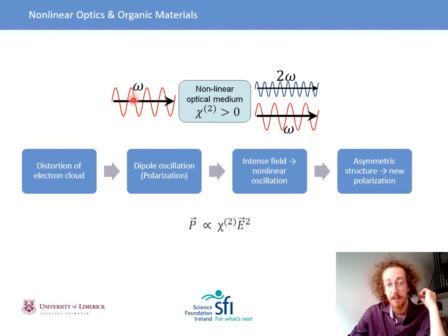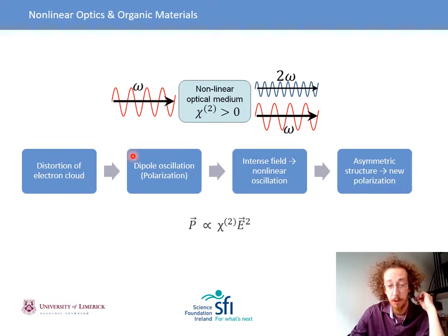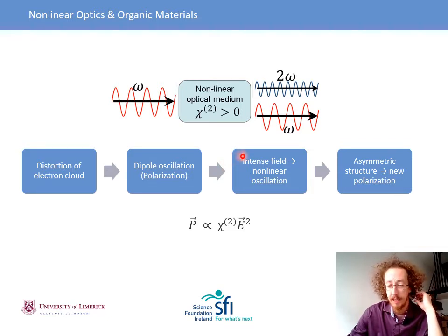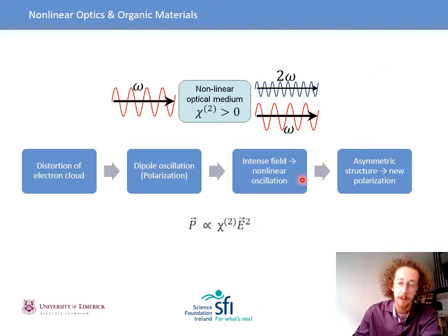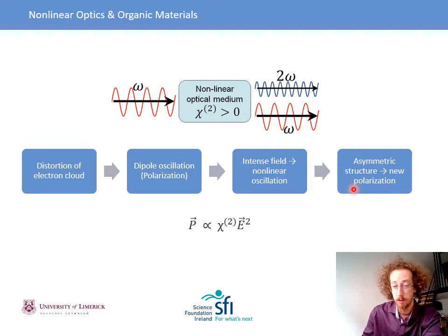Say you have a laser of frequency omega shining onto a non-linear medium — you have a distortion of the electron cloud, which causes dipole oscillations, the effect of which manifests as a polarization. Because we have this intense electric field, we can model this dipole oscillation as a non-linear oscillator, so we get new frequency components emerging that are different from the incident. And if you have an asymmetric structure — this refers to crystal symmetry — if there's no axis of symmetry in the crystal, you get to keep these new polarization components.